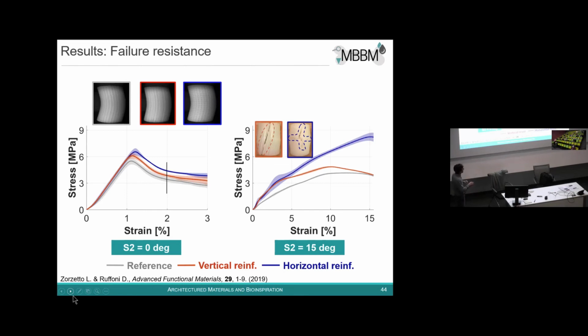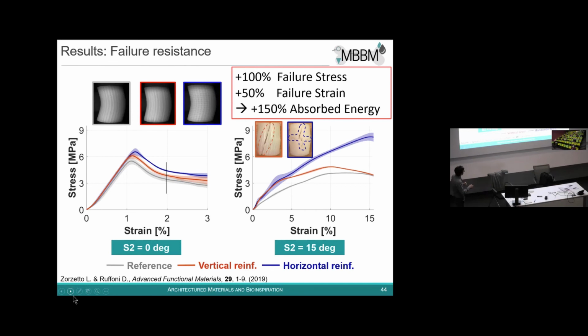examine the post-failure structures. In the case of vertical reinforcement, we see a long crack running through the system. And in the case of horizontal reinforcement, we see that the crack at some point also runs diagonal. So we are also tuning the way it breaks. And because of this, we have a 100% increase in failure stress, a 50% increase in failure strain, and a structure which absorbs 150% more energy.